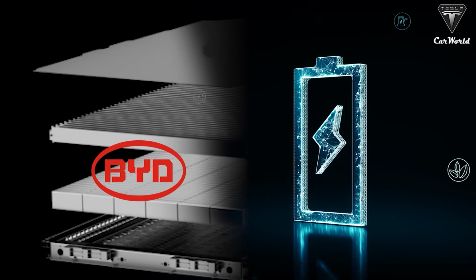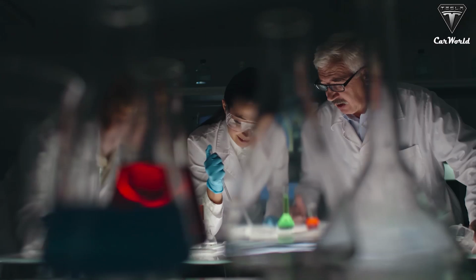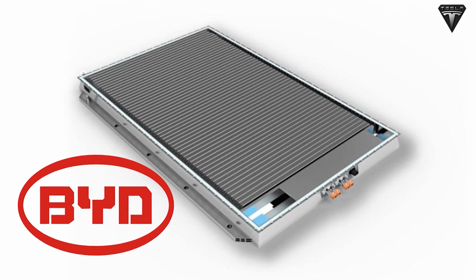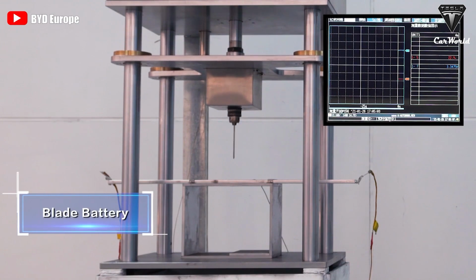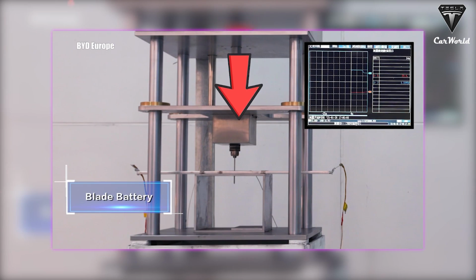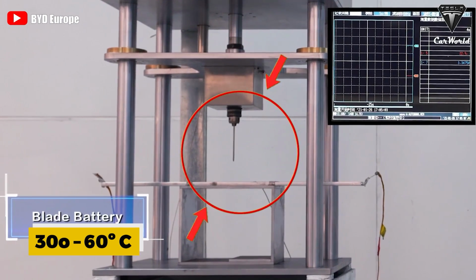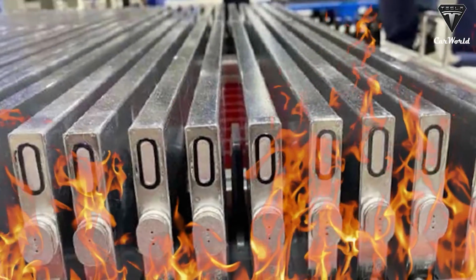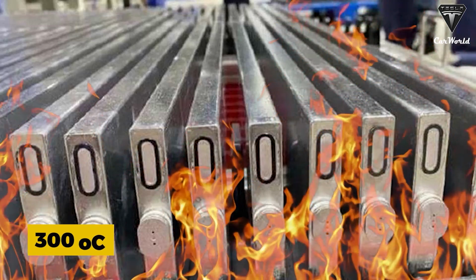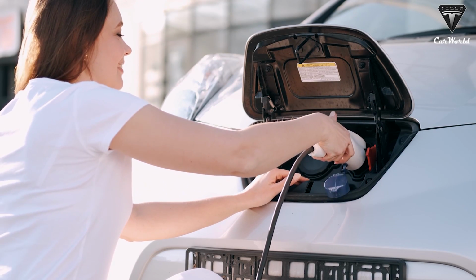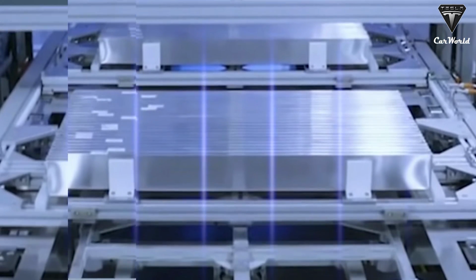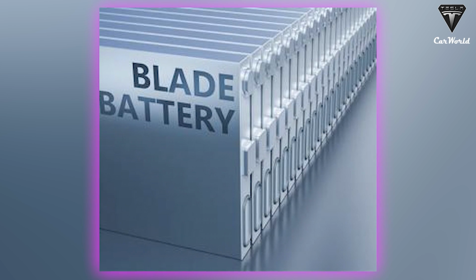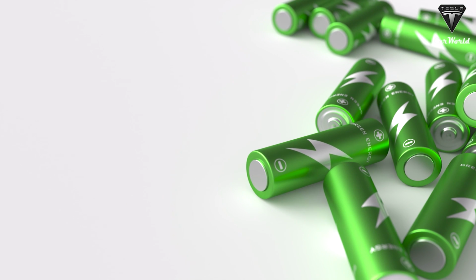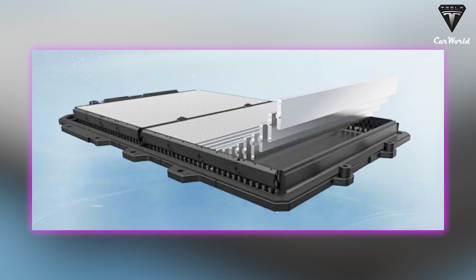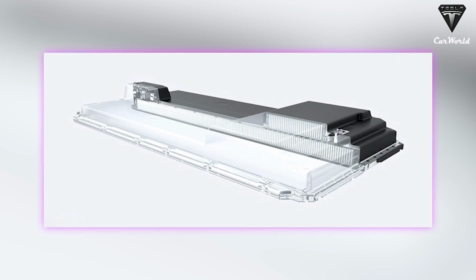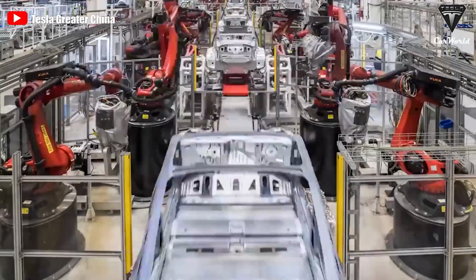LFP is a more stable battery chemistry, even at temperatures as high as 500 degrees Celsius. Following an exhaustive development program, the Blade battery returned truly impressive class-leading test results where a stringent nail penetration test confirmed the Blade battery's surface temperature reached a remarkably low 30 to 60 degrees Celsius, all while emitting no smoke or fire. Further tests subjected the Blade battery to a 300 degrees Celsius furnace test and a 260% overcharging test, neither of which resulted in a fire or explosive response. The results provide evidence that the Blade battery dramatically outperforms traditional ternary lithium batteries and lithium iron phosphate technologies. This compact design, coupled with class-leading safety credentials, offers a marked competitive edge for BYD and, moreover, a step change for the entire EV industry.